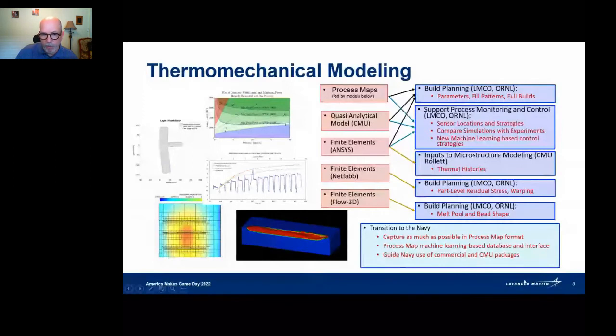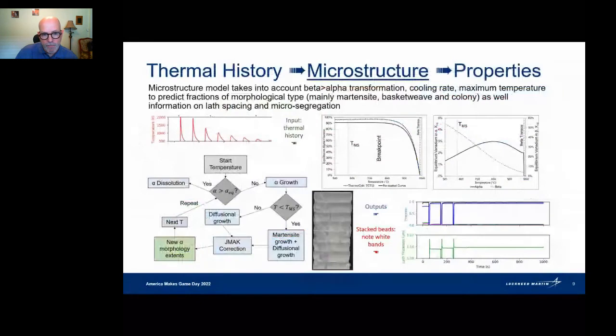So the next step in our workflow is to take that thermal history, and this is where Tony Rollett's group would come in and use that thermal history to understand what the material state is for that particular build. And so these microstructural predictions would take into account, again, the detailed thermal history within each cycle for the TI-64, mainly for the influence on the previously laid beads. And so the subsequent heating is really important to understanding that morphology.